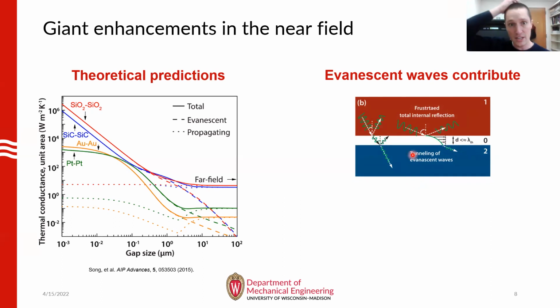Now, despite these interesting theoretical predictions, experimentally studying near-field radiative heat transfer is technically very challenging. For example, how do you practically achieve stable nanometer-sized gaps? Also, how do you eliminate other modes of heat transfer, like conduction through air molecules or surface contaminants, which could increase the uncertainty in your measurement? On this slide, I want to show you a measurement approach I helped develop, which allowed us to overcome a lot of these technical challenges.